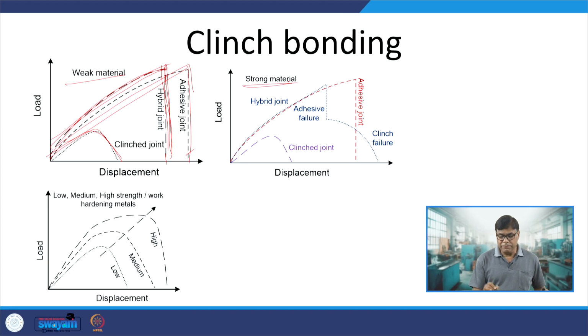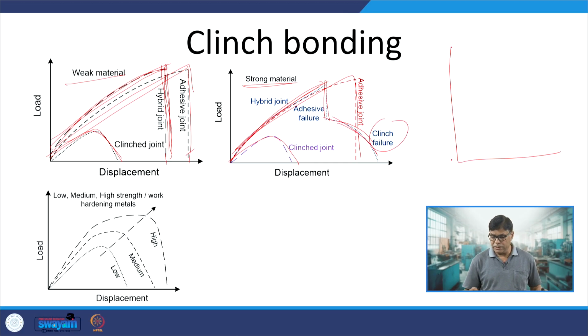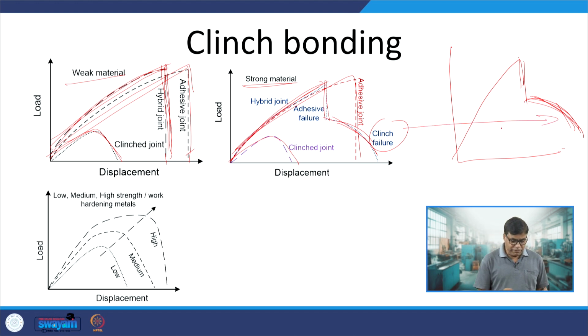But when we use workpiece materials which are stronger, the clinch joint goes like this and the adhesive joint fails like this. But in hybrid joints, initially the adhesive will fail and then the load is taken by the clinch. So, this section indicates the adhesive failure, and then the clinching joint will come into action, which corresponds to the clinch failure. So, when we have low, medium and high strength or high work hardening metals, our curve changes accordingly.